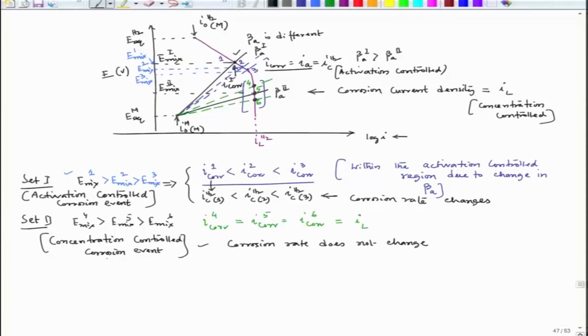But remember, we could see the change in the corrosion potential, and now in this concentration side we could see that in case of situation 4, and if we consider the situation 5, E mix 4 is greater than E mix 5. So, I could think that in situation 4 I could ennoble the metal compared to situation 5, but even if we ennoble it, still I could say that the corrosion rate does not change, the corrosion rate still remains at i_L. So, that suggests that ennobling of a metal does not mean that every time it will have decrease in corrosion rate.